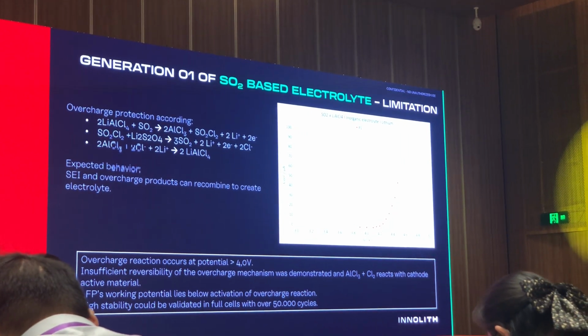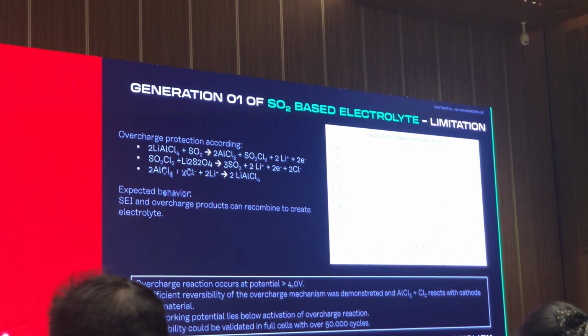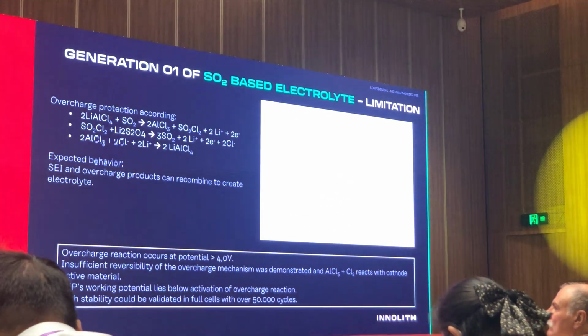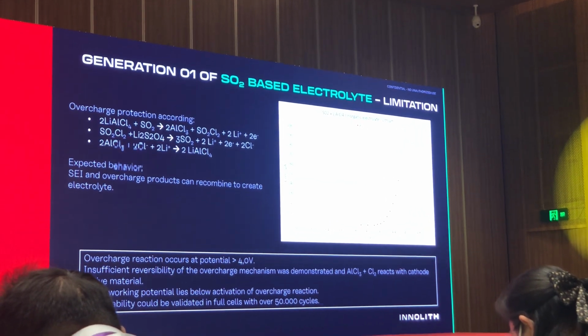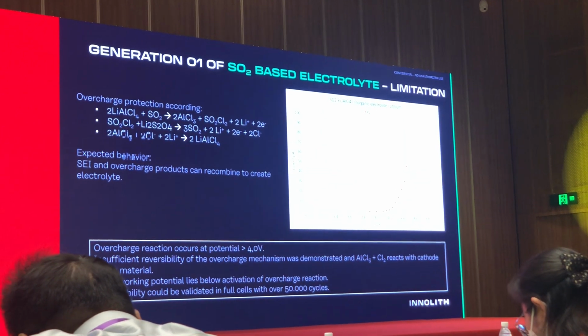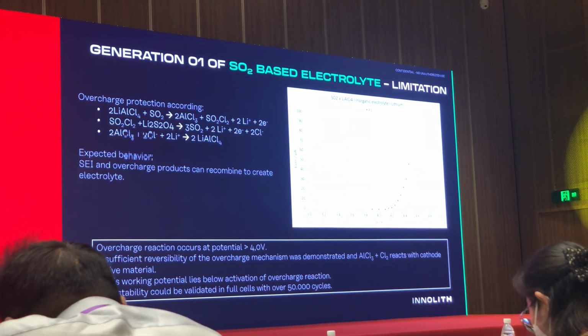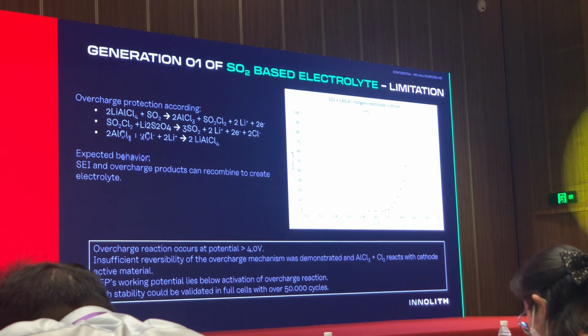of the electrolyte. By investigating deeper, we found out that the chloride was oxidized, forming chlorine reacting with the solvent, producing sulfur chloride, which was then also reacting with other compounds in the system. So the limitation could not be overcome